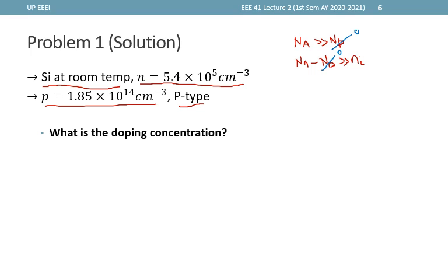We ended up asking that question since we want to use the approximation that p is approximately Na, and we can only use that given these assumptions. So if we assume that we can use that, then verify the assumptions, the question simply translates to, is p much greater than ni? P is 1.85 times 10 to the 14, and yes, it is much greater than ni.